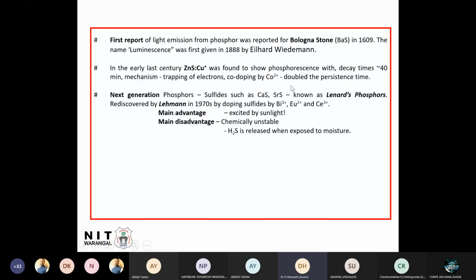But the main problem was they are chemically unstable, because sulfides, when they come in contact with moisture, release H2S gas, and then they become oxide material. So this was the main instability feature with sulfides. So they thought it's only the sulfides which can do this type of thing.